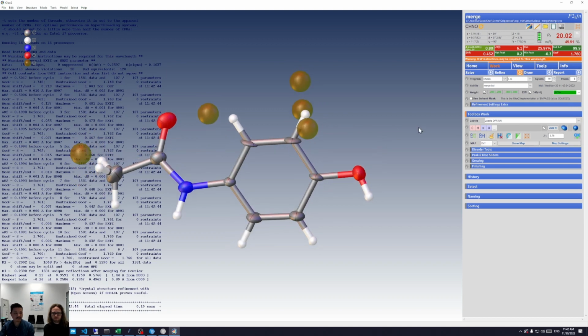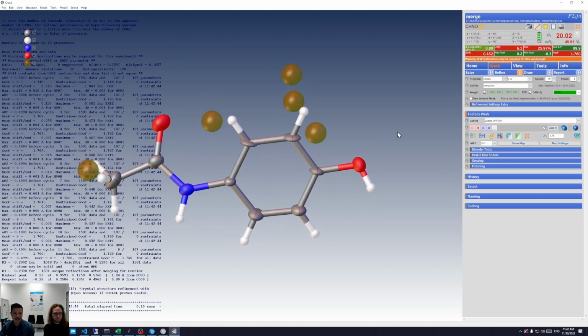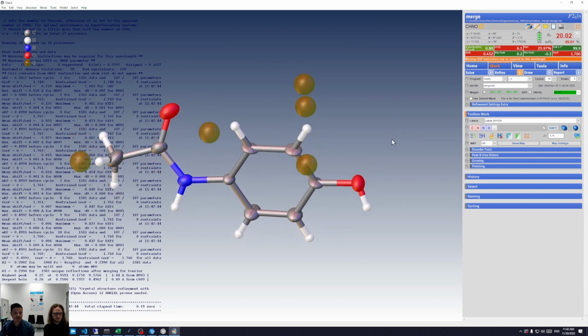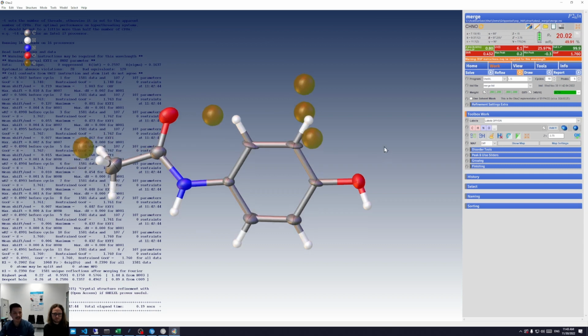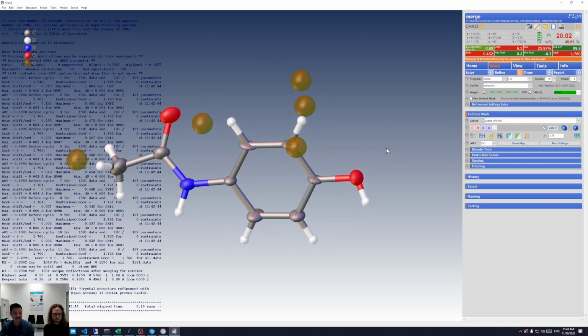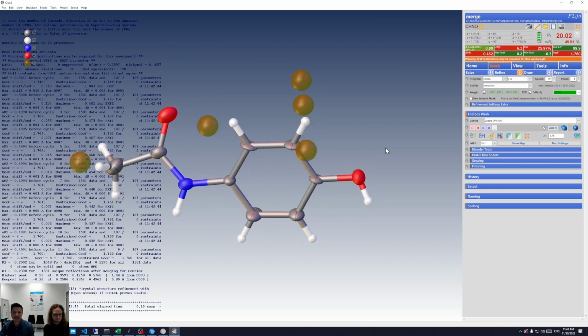As you can see, it was a quite straightforward structure. All the ADPs look fine in this case. We have a 99.9% completeness. I over sigma and R int are a bit high compared to X-ray structures, but that's normal. We have dynamic effects here in this case. So I think for electron diffraction, you often have to, let's say, readjust your expectations concerning those metrics a bit.